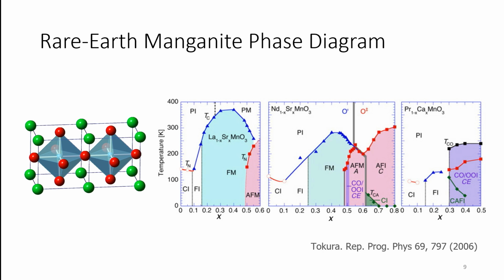So for example, in this blue region here, where you have between 15 to close to 50% of strontium replacing the lanthanum, the material is a ferromagnetic metal. And this material has a very interesting property where if you apply a magnetic field to it, you can actually modulate the resistance by a very large amount. So by just changing the chemistry at these lattice sites, you can have the ferromagnetic metal at room temperature and below room temperature. You can have an insulating phase here if you get your strontium close to 0. And in this red region here, the material is an anti-ferromagnetic metal.